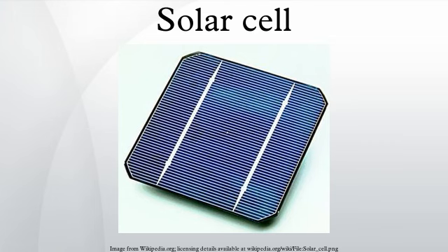Polycrystalline silicon wafers are made by wire sawing block-cast silicon ingots into 180 to 350 micrometer wafers. The wafers are usually lightly p-type doped. A surface diffusion of n-type dopants is performed on the front side of the wafer. This forms a p-n junction a few hundred nanometers below the surface. Anti-reflection coatings are then typically applied to increase the amount of light coupled into the solar cell.